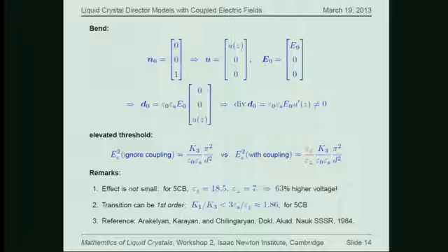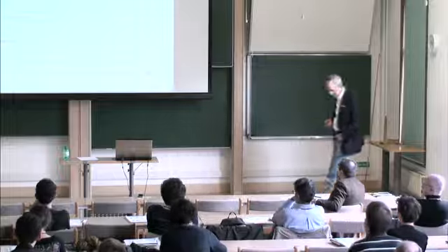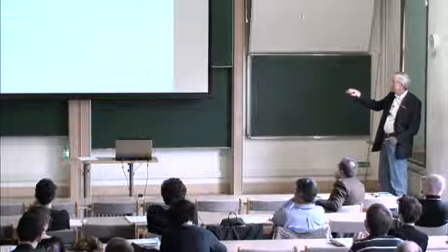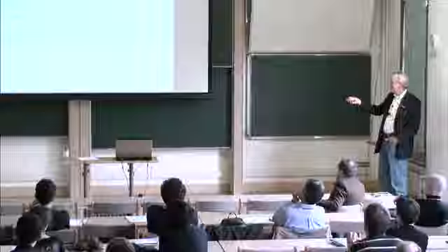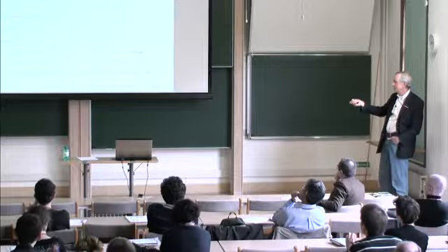The other thing that doesn't come out of this analysis, but I was made aware of by Peter Palffy from some experiments that he had done with a former PhD student of his, Barbara Frisken. Not only is the transition elevated here, but the transition can be first order or second order, depending upon a simple relationship between the elastic constants and the dielectric constants.